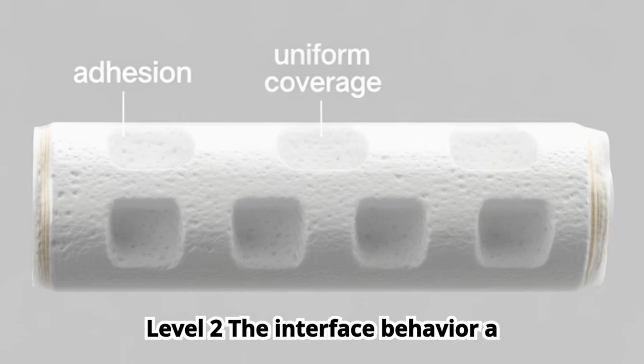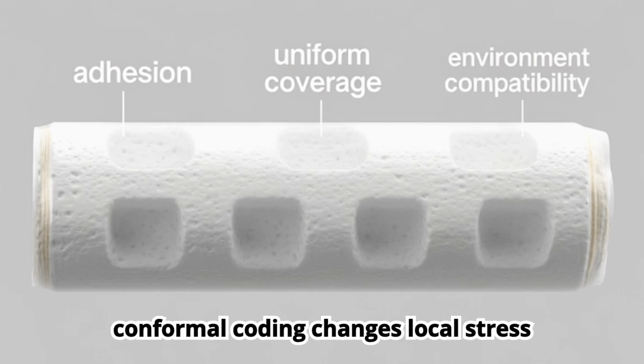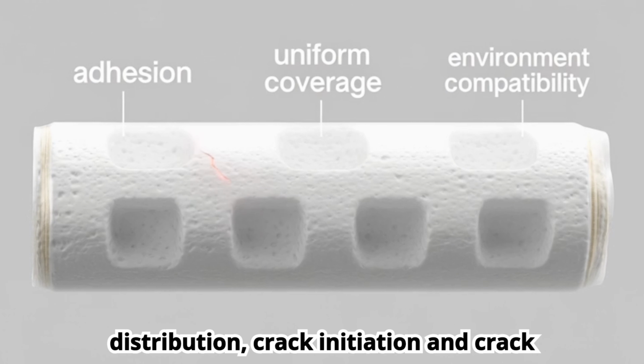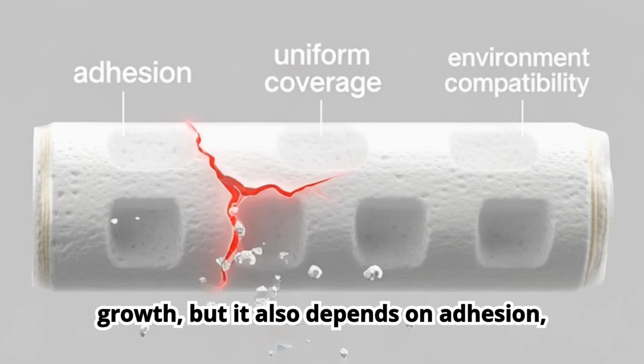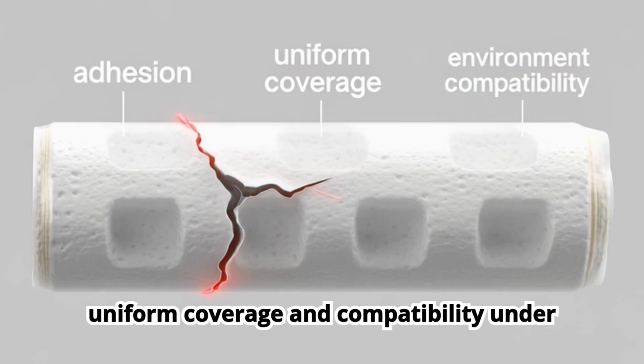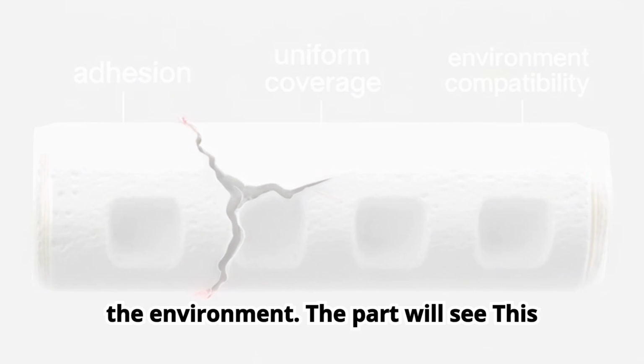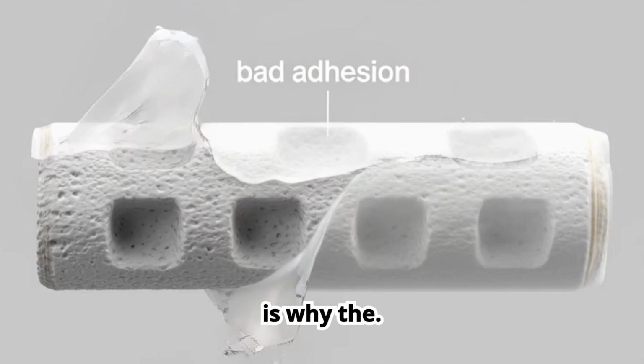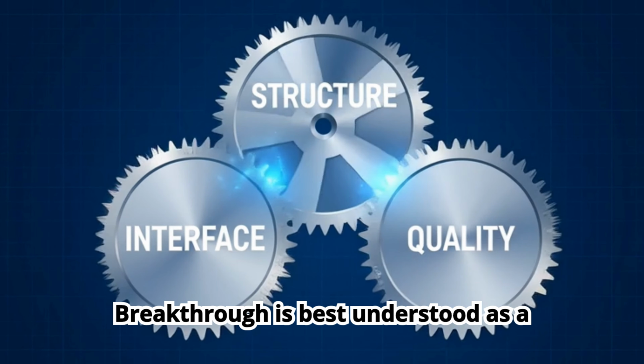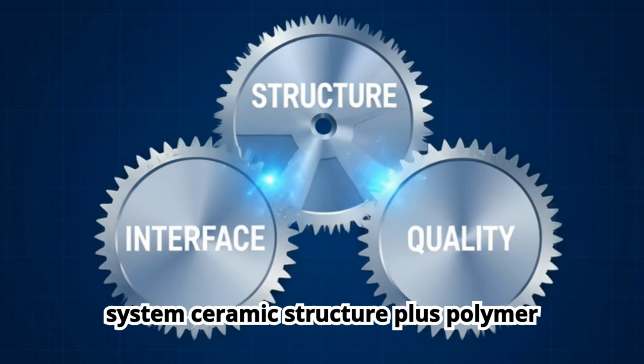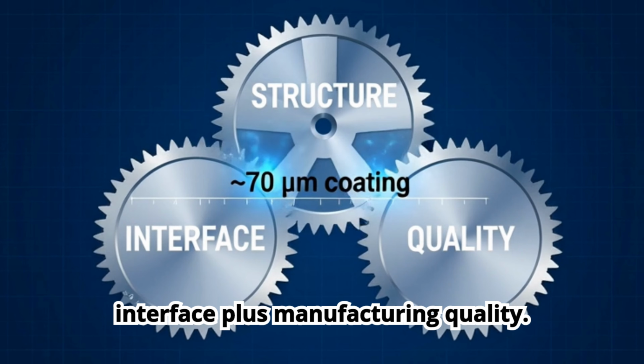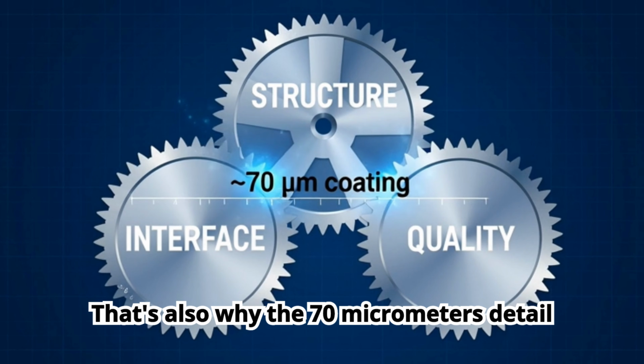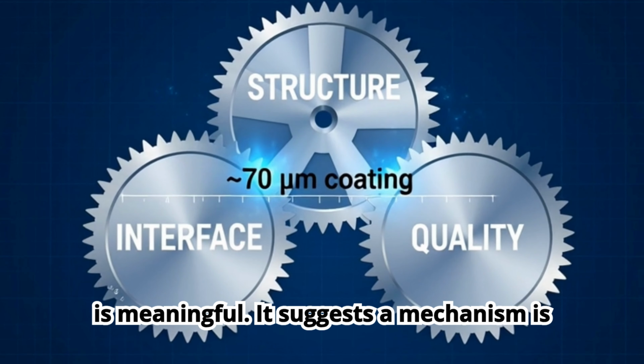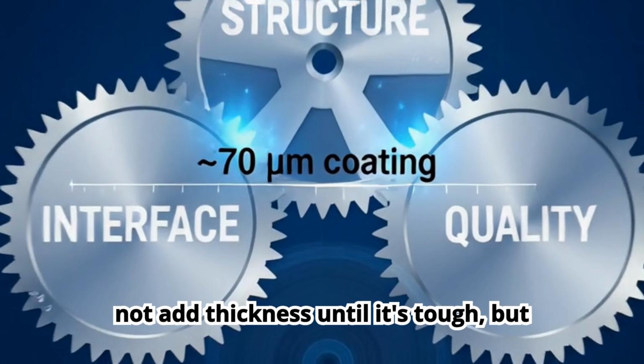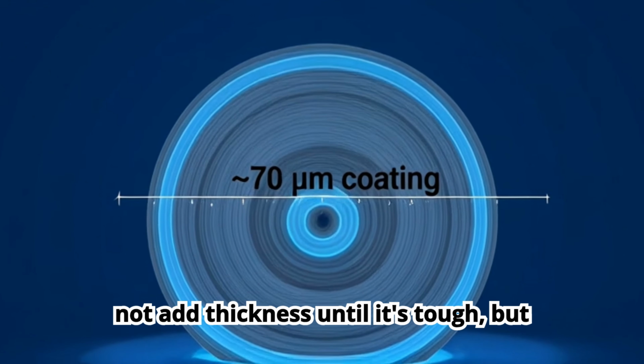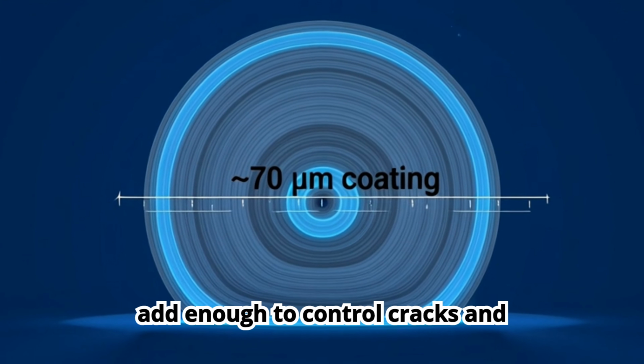Lever 2, the interface behavior. A conformal coating changes local stress distribution, crack initiation, and crack growth. But it also depends on adhesion, uniform coverage, and compatibility under the environment the part will see. This is why the breakthrough is best understood as a system. Ceramic structure plus polymer interface plus manufacturing quality. That's also why the 70 micrometers detail is meaningful. It suggests a mechanism: not add thickness until it's tough, but add enough to control cracks and dissipation.